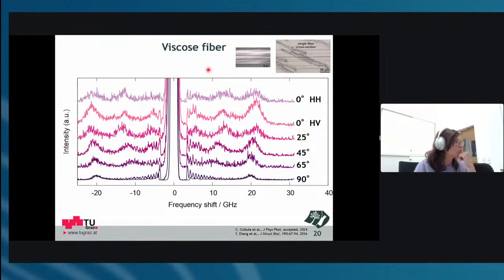And as it turned out, it was pretty nice to measure, but there was one thing that was really weird. So we started out in the horizontal alignment of the fiber, so we would measure directly into the axial direction of the fiber. And when you look here, you see the spectra at all the different orientations. For the zero alignment, when the fiber is horizontal, I show you the two polarized spectra. When we have the polarizers in HH and do the measurement, we should only get the longitudinal mode. There is only one longitudinal mode that should be possible to see. And here already the weird thing started, because as you can see, here are two bumps. So there are really two peaks showing up.